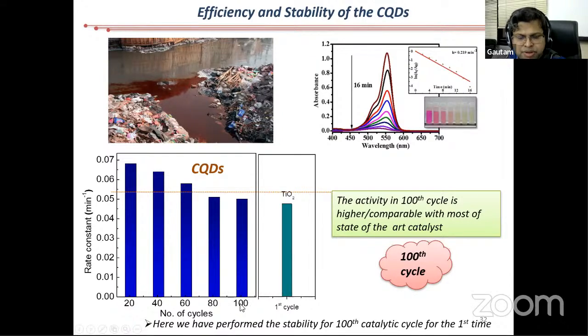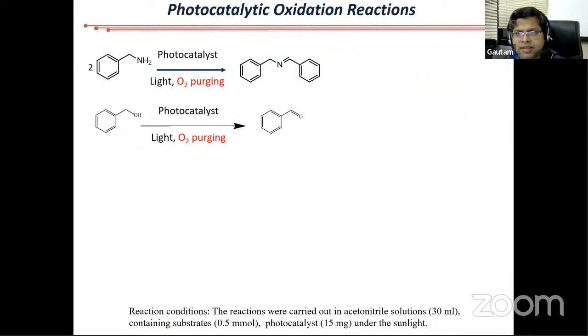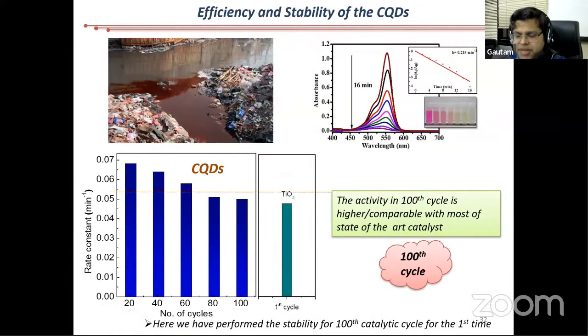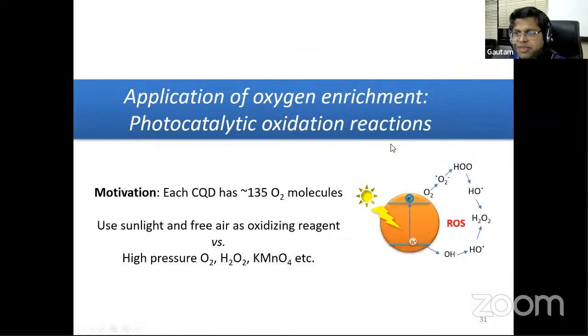One catalyst has degraded such colored materials 100 times. It is still very, very good compared to a standard material, something like TiO2. TiO2 is the first catalyst where this phenomenon was discovered. And this is very, very active. This degradation happens because of the ROS.